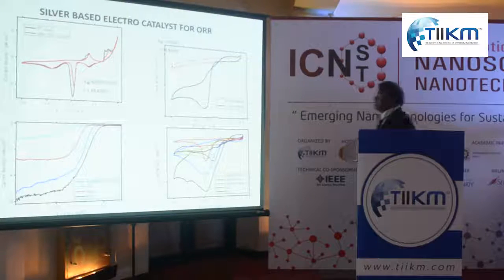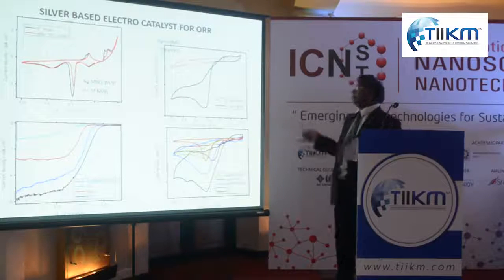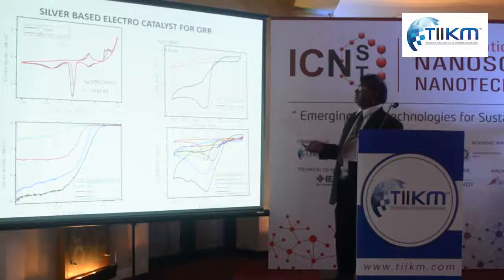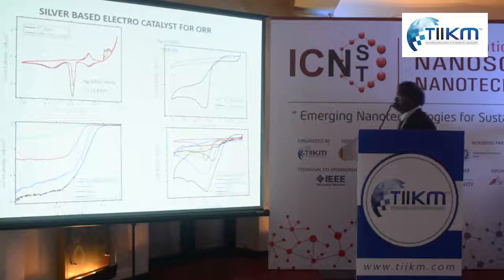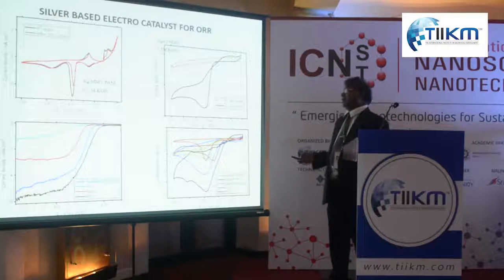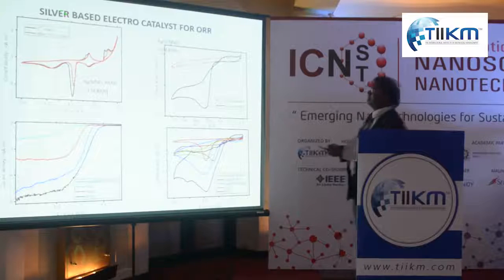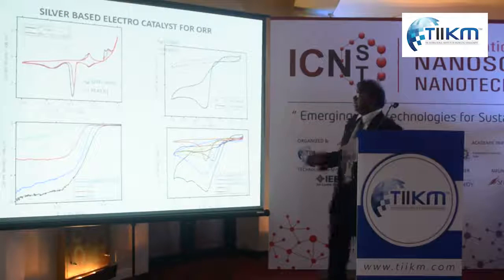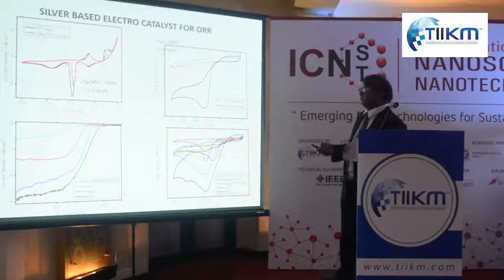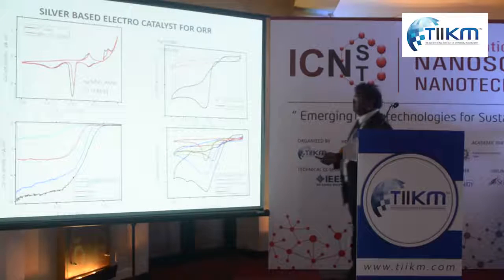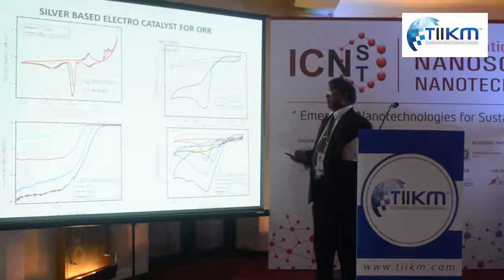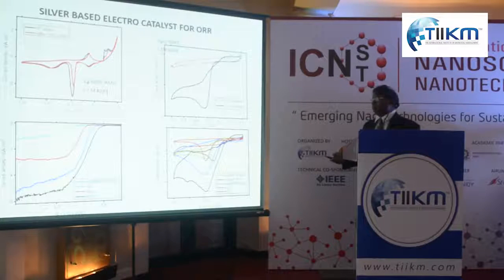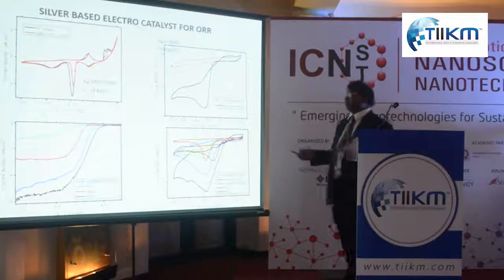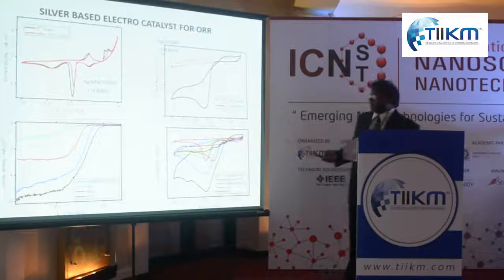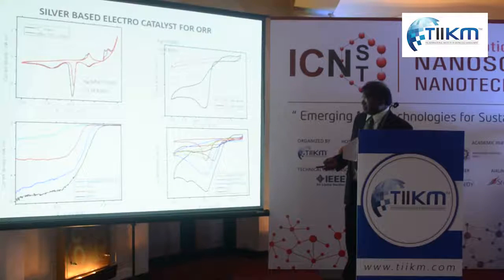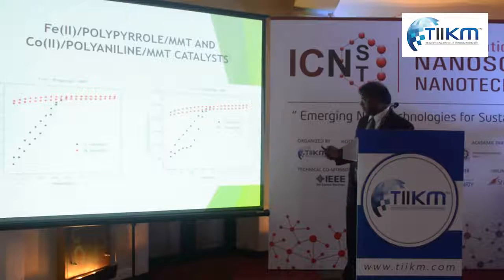And then there's Chaturanga. He developed 19 such catalysts. He used different cations to oxidize and different monomers like aniline, pyrrole, and 3,4-ethylenedioxythiophene, which we call EDOT. When you polymerize aniline, you get polyaniline; pyrrole polymerizes to give polypyrrole; and EDOT to PEDOT. Most of them work, yes, silver ions, even silver ions can do the job.